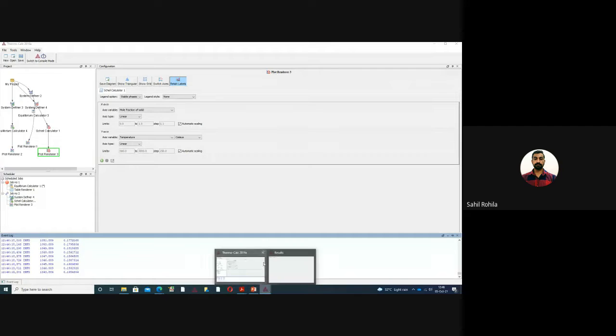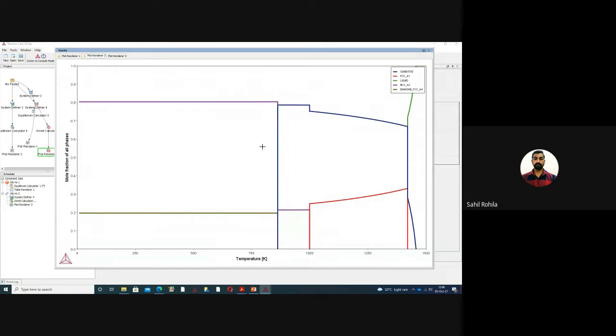Earlier, as we obtained this property diagram, it was telling us that the liquid is the green line. Above this temperature, above 1423 degrees centigrade, our phase will completely transform into liquid phase. So Scheil solidification is a reverse of the property diagram. It will start from liquid, then the first phases which will crystallize are cementite and FCC. So if I reverse this property diagram, I'll get the Scheil solidification.